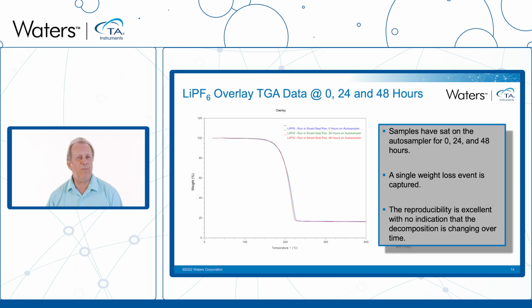So we took 3 samples of LiPF6 powder, we sealed them in the TGA Smart Seal pans, placed them on the autosampler. We ran 1 sample immediately, we ran 1 sample after 24 hours, and we ran the 3rd sample after 48 hours. From this, you can see a single weight loss event is captured in all 3 of them. The reproducibility is excellent, and there's no indication that the decomposition is changing over time. Therefore, no indication that these samples are being exposed to any type of water vapor. So again, we see that the hermetic seal quality here is excellent, and these samples are staying in the dry state during decomposition.